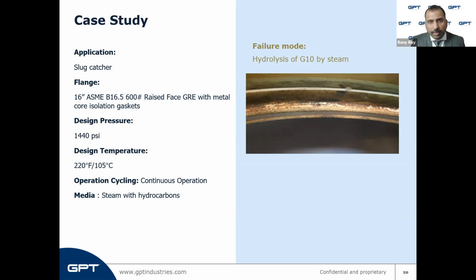The pressure was approximately 1440 psi and the temperature was 220 degrees Fahrenheit or 105 degrees Celsius. The media was hydrocarbons with steam and the application was a slug catcher. Analysis shows that the epoxy in the glass reinforced epoxy became hydrolyzed by the steam.